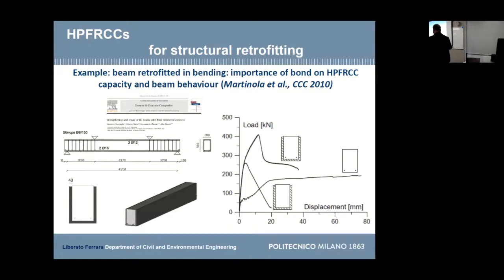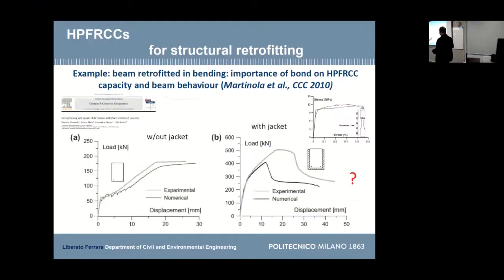One important thing is this. This is a paper which was published about 10 years ago, in which they used this material for jacketing. So it was meant for shear and bending retrofit. And then they made some calculations, some design, and they realized that, okay, well, if we predict our ordinary reinforced concrete, our models are very good. But if we predict with retrofitting, what does it happen? The prediction is much higher than the experiments. So this means that our model is not on the safe side. Well, because what did it happen?